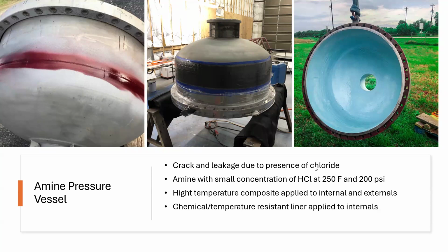This was cracking due to presence of chlorides, which was due to a small concentration of HCl. HCl, hydrochloric acid, is going to be an aggressive chemical towards coatings, and amines can also be aggressive. So you have to make sure you're using your high grade coatings when it comes to some amines. So here we had amines, small percentage of HCl at 250 and 200 psi. That's high temperature. That's also high pressure for coatings. So you definitely want to apply everything correctly, do the best possible surface prep, and use the best possible product.